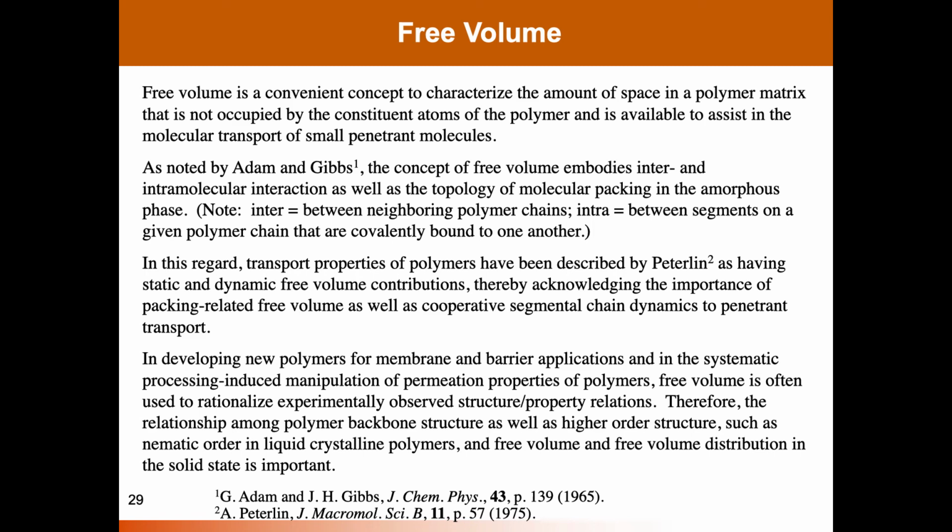Now the polymer chains are moving in ceaseless thermal motion, and this gives rise to a dynamic contribution to free volume that is often regarded as being responsible for penetrant transport or gating penetrant transport in polymers. It turns out we don't make much of a distinction between static and dynamic free volume, one because we can't measure them separately, at least in the laboratory, and two, because they're often highly correlated. If you have large levels of static free volume, then you're likely to have high levels of dynamic free volume as well, because the polymer chains are further apart and can in principle execute motion easier.